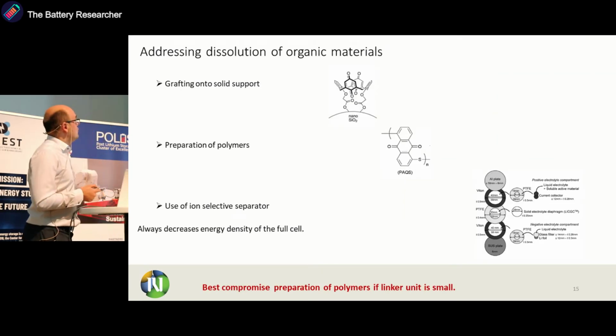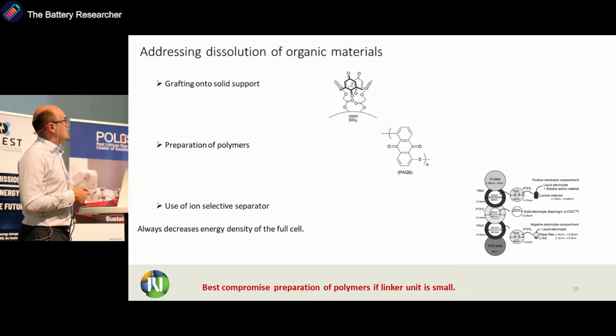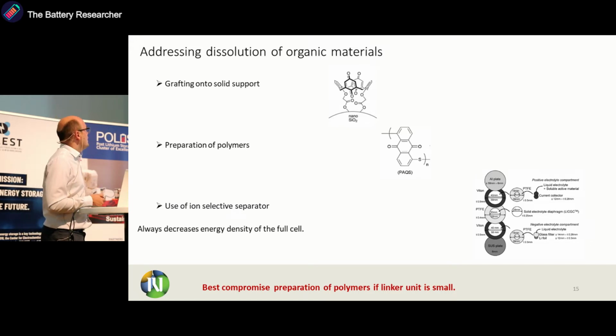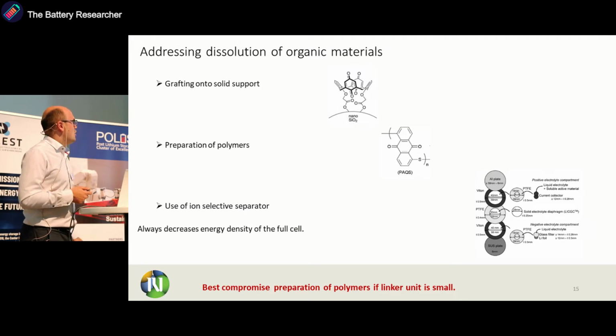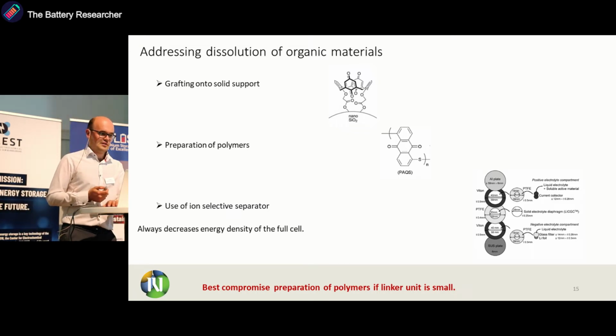And we have quite some organic battery field. There are some quite basic approaches to address the dissolution of organic materials, and we can graft them onto solid support, like here, which is putting them on silica. We can prepare polymers and increase their molecular weight and make them less soluble, or use ion selective separator. Each of these approaches comes at the cost of decreasing their gravimetric energy density.